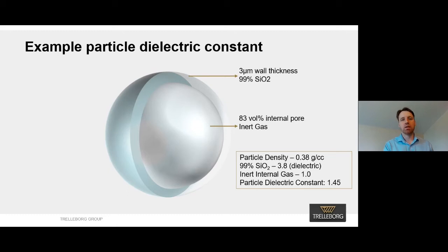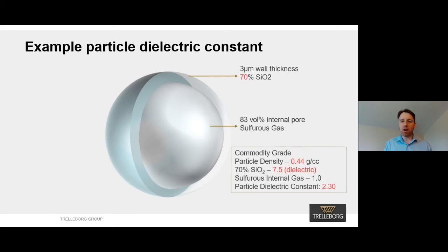Now, if you compare that to a commodity-grade glass microsphere with the same shell thickness, the commodity-grade glass microspheres are generally made of soda-lime glass, which is only 70% silica. The other 30% is mostly sodium. And so you can see the particle density rises to 0.44. It's a higher density because the glass actually has a higher density. And the glass making up the wall has a dielectric constant of 7.5, resulting in a net particle dielectric constant of 2.3.